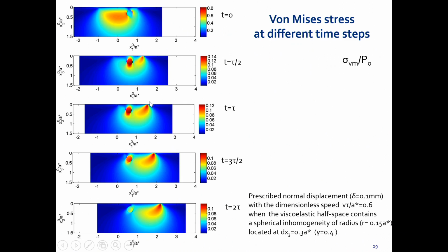Okay, then you can see here the inclusion. Now the load is moving. Of course, in front of the contact, you have something which is not anymore axis symmetric for the Hertz solution, because when you indent viscoelastic material, the solution is always axis symmetric when there is no indent. Now when you move, because you have a peak of pressure in the front of the materials, you have some stress concentration that you can see here, which is this one.